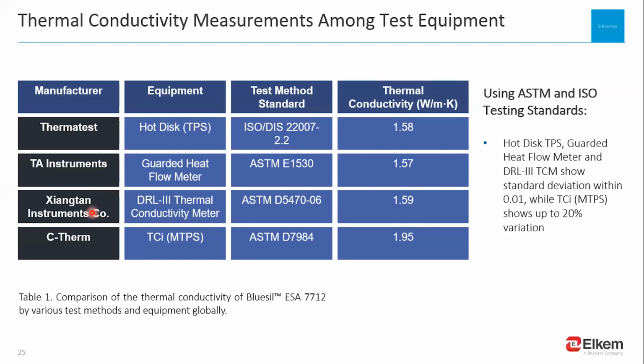However, the outlier test results yielded from the C-Therm TCi device under ASTM D7984 were greater than 20% deviation from the other equipment and test method standards. Fortunately, the ThermTest Hot Disk test method aligned closely with the application for the EV customer, so it was chosen as the correct method for estimating thermal conductivity.